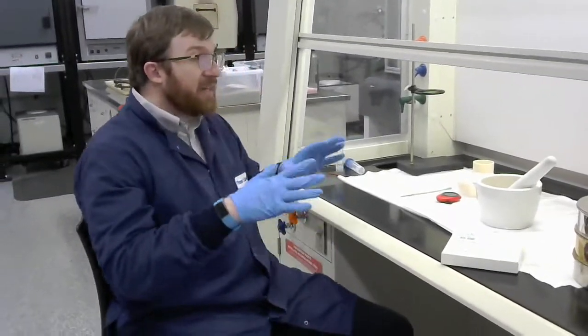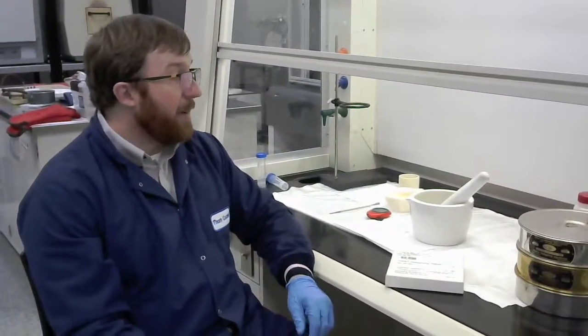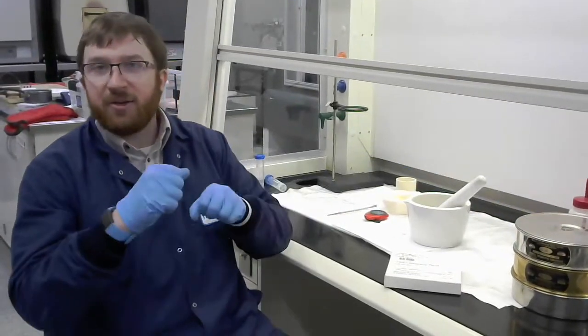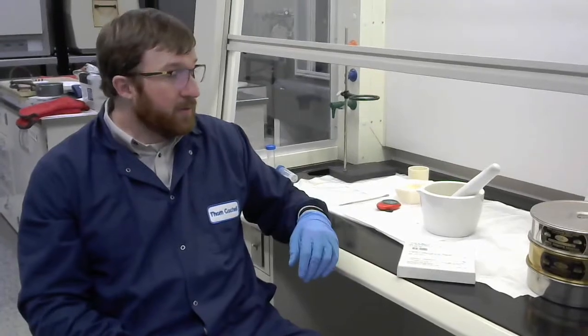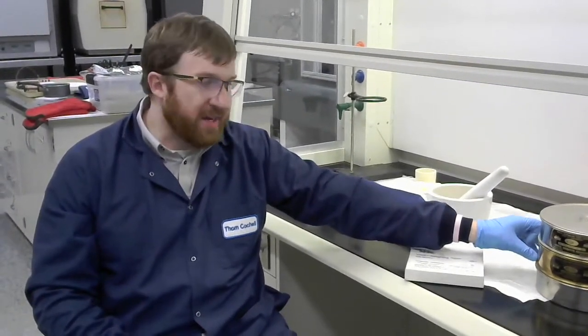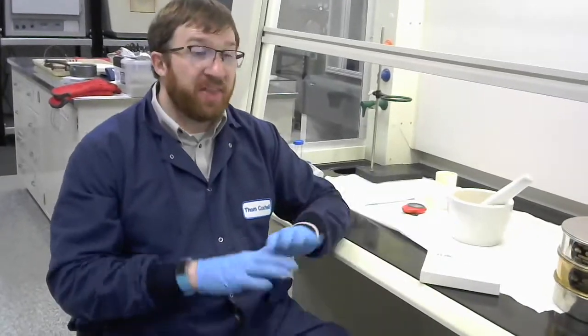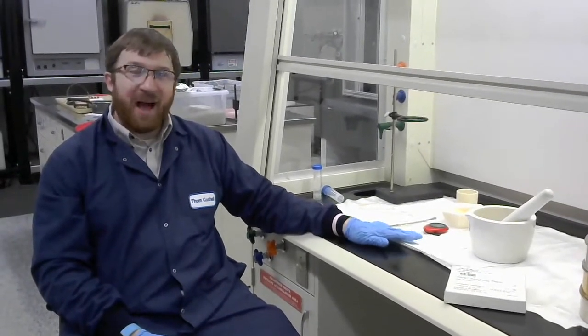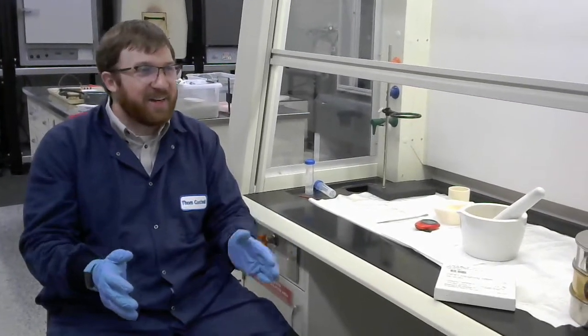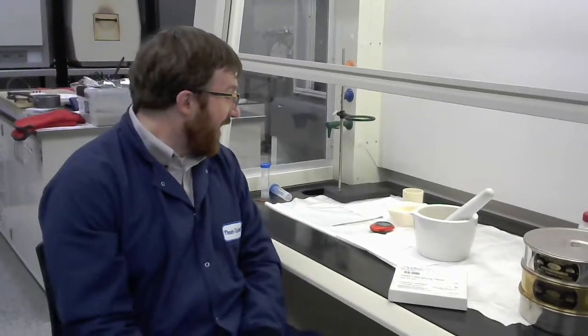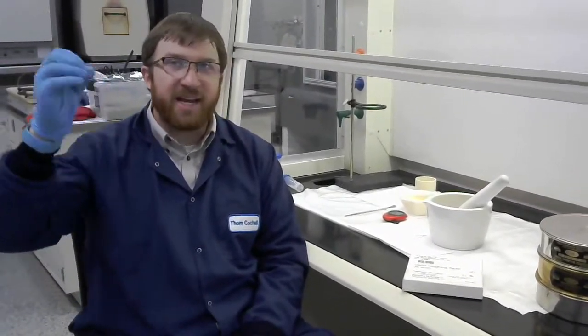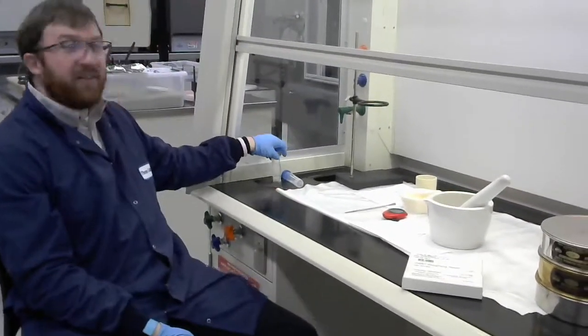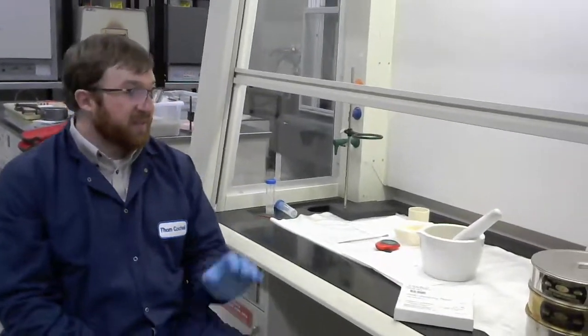So, I'll kind of end it here, but just to kind of illustrate what we're going to do with the remaining, is again, I'm going to take the stuff that didn't make it through the 80 first and try to get those big clumps out. And then I'll add that back in. And then once we get everything through, I'll take the stuff that hasn't yet made it through 325 and we'll add all that back to the mortar and pestle and we'll keep going until I've got all of it through here. And so then we'd be done for this group. I'm working still on Wednesday A's powder. And so we will be done with Wednesday A's powder. Antonio is in the other hood. We're both listening to podcasts and music right now. And so he's going to be working on Wednesday B's powder and he'll do the same thing. So we'll try to take a few pictures along the process, but at the end, we'll have a nice powder that is ready to go for dry pressing and sintering. And so we'll show those as we get to them. So stay tuned for those.